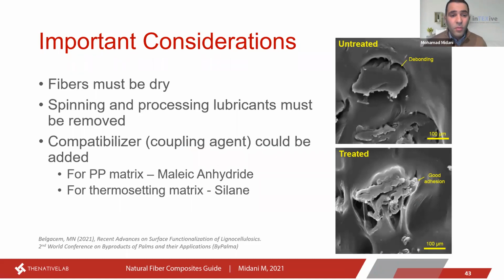So the first and the most important consideration is that we need to dry the fibers, okay? Or at least make sure that the supplier is providing a dry fiber, okay? Because as I said, natural fibers have a natural tendency to absorb moisture from air, and their moisture content in normal conditions can reach up to 8 or 9%. And this would significantly lower the performance of the composite. It can reach up to a 30 or 35% reduction in the mechanical performance. This is something that we need to avoid.